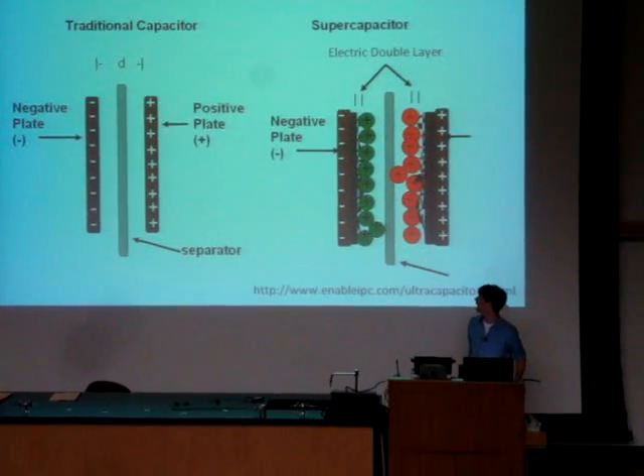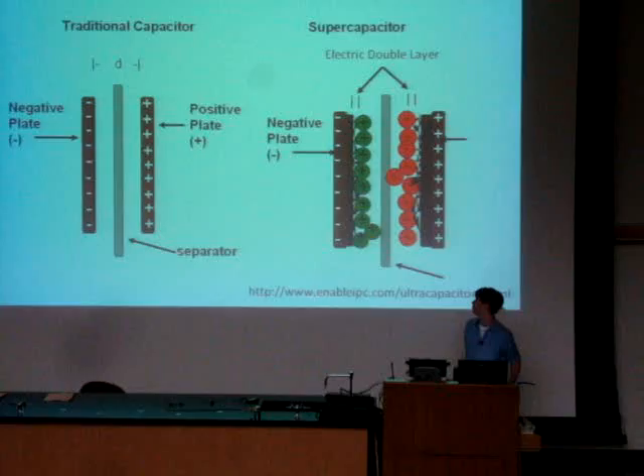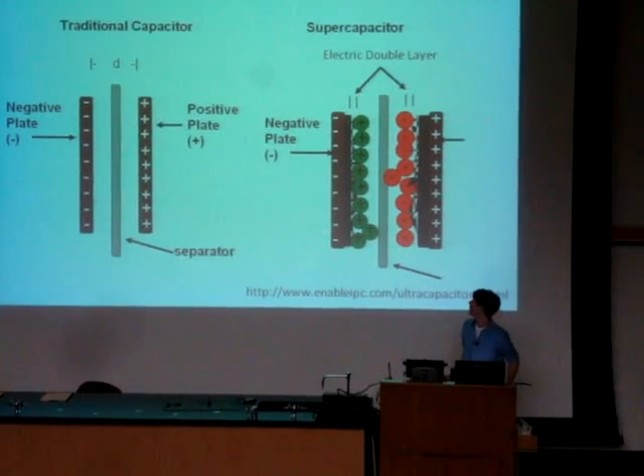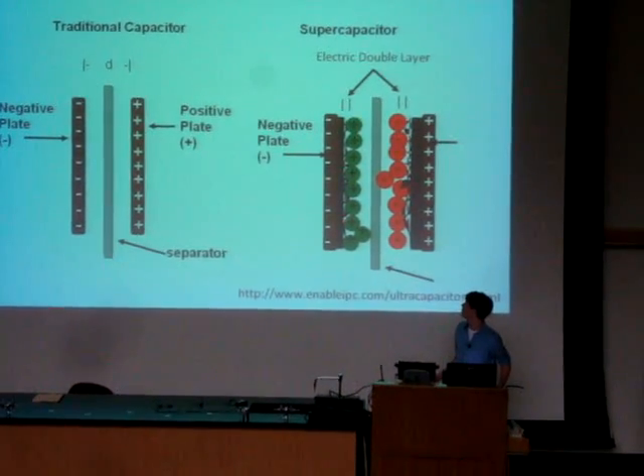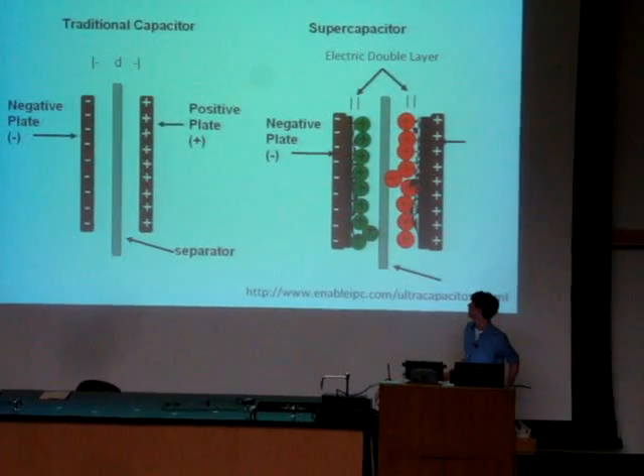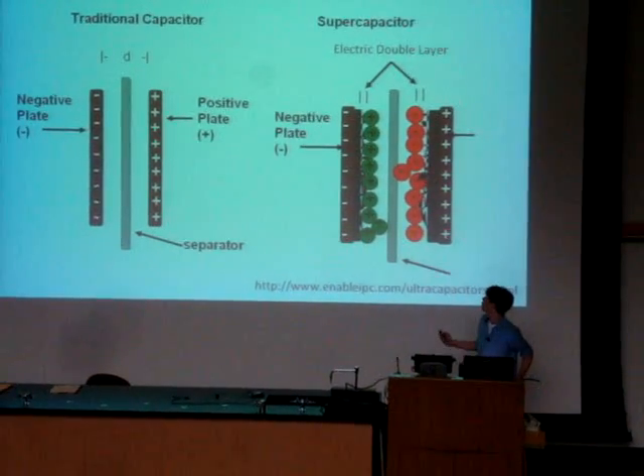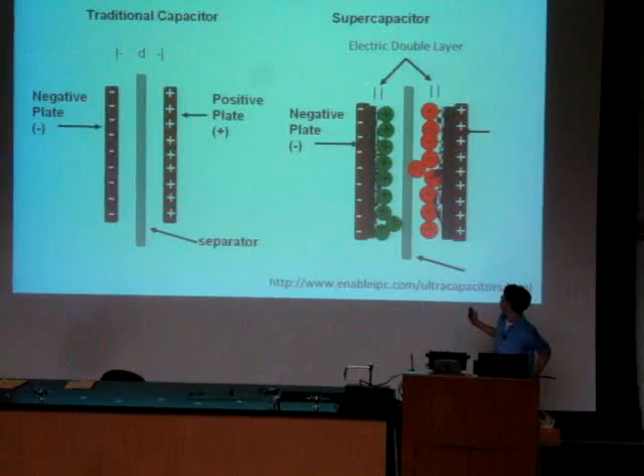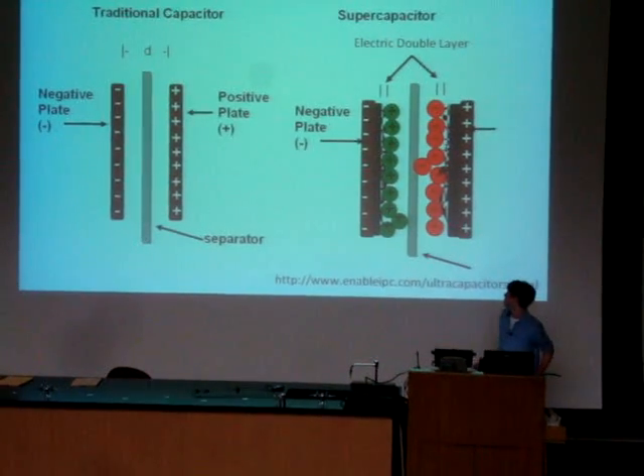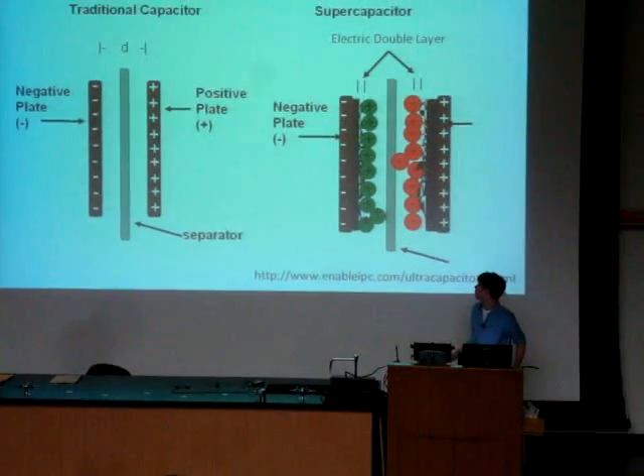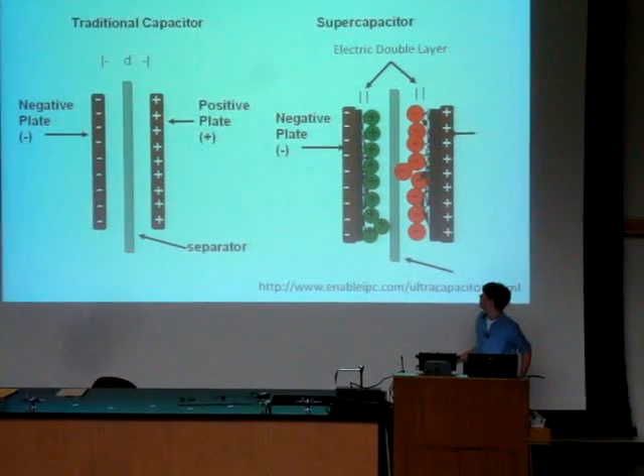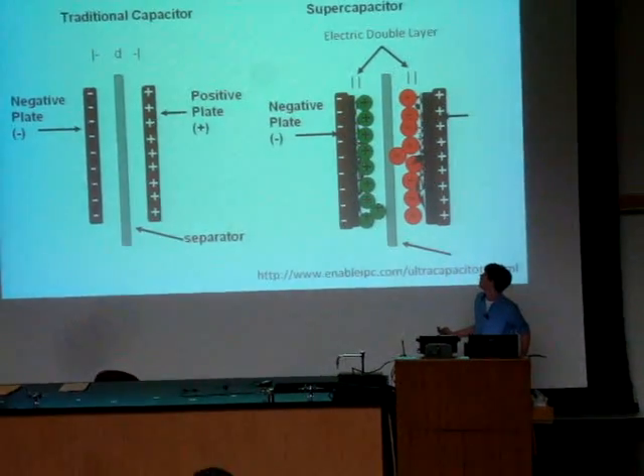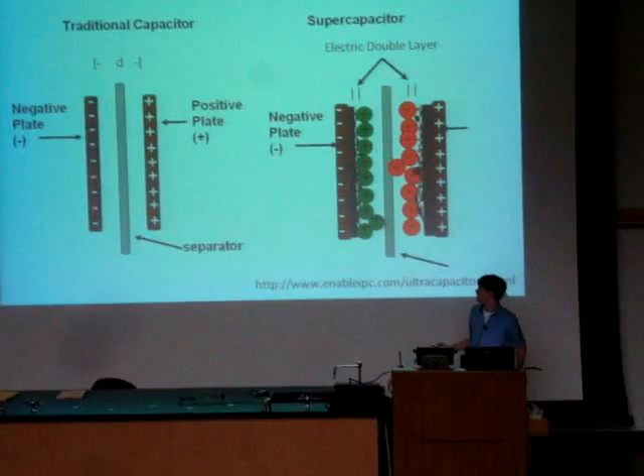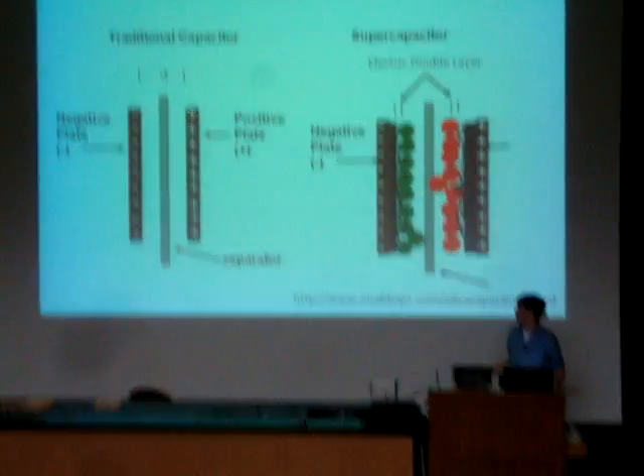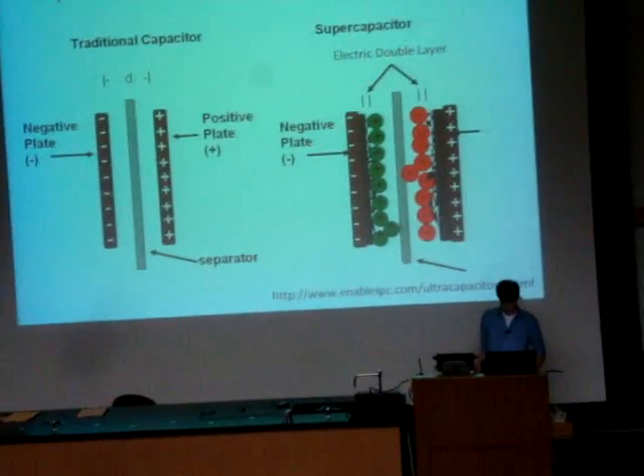Supercapacitors work by including a highly porous material in an electrolyte solution. Upon charging, the ions in the electrolyte solution end up associating with oppositely charged plates. So now there are actually two capacitors in series with one another, with the distance on the scale of nanometers or even angstroms. This causes a great increase in the capacitance, making it reach levels of farads to kilofarads, over the regular capacitors' pico to microfarad levels.